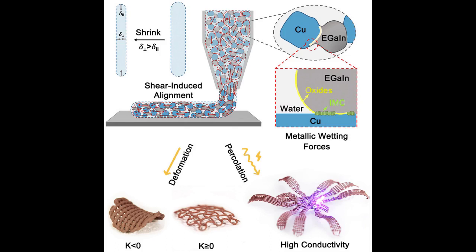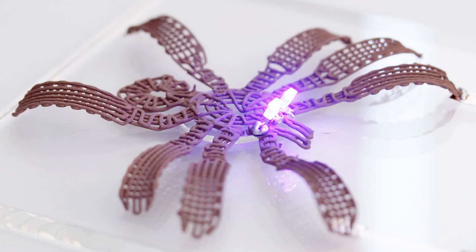The researchers found that the alignment of the particles influences how the material dries. For example, if you printed a cylindrical object, the sides would contract more than the top and bottom as it dries. If drying occurs at room temperature, the process is sufficiently slow that it doesn't create structural change. However, if you apply heat — for example, put it under a heat lamp at 80 degrees Celsius — the rapid drying can cause structural deformation.